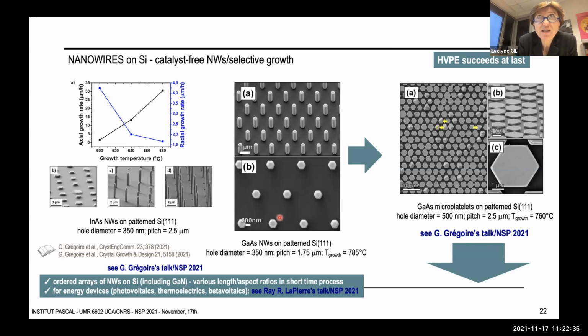No, because when you want to dope the nanowires with silicon, we have a rich vapor phase which contains a lot of silicon atoms with silane gas. So the silicon atoms come from the vapor phase. It's much larger than the silicon that you can have in the droplets because of the effect of substrate. So the main input is from the vapor phase, which is completely controlled. So you don't have any decrease of the doping level as the nanowires grow. Okay, I understand. Thank you.